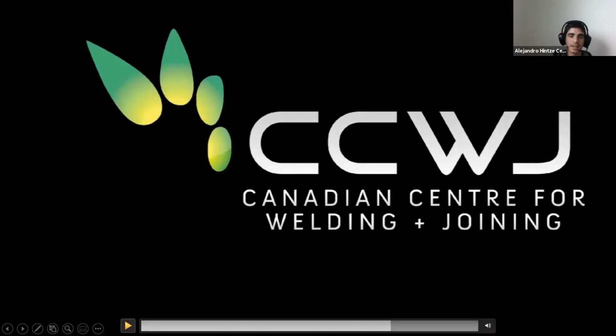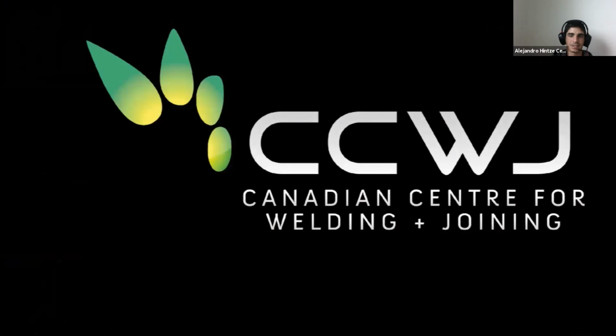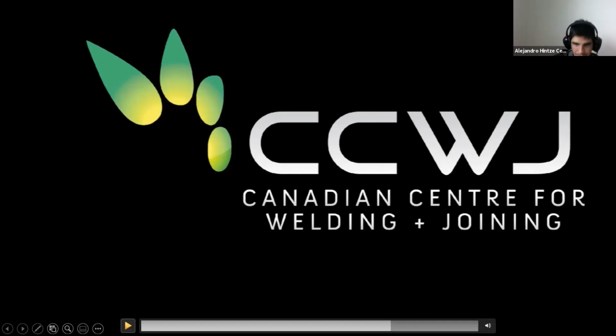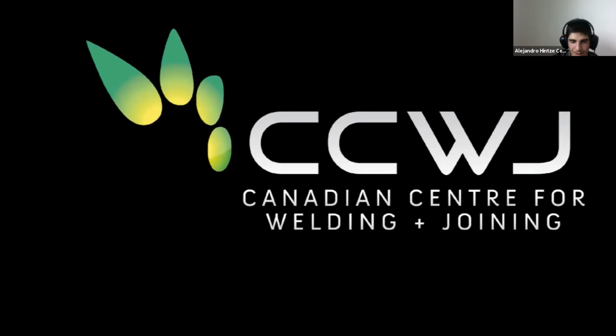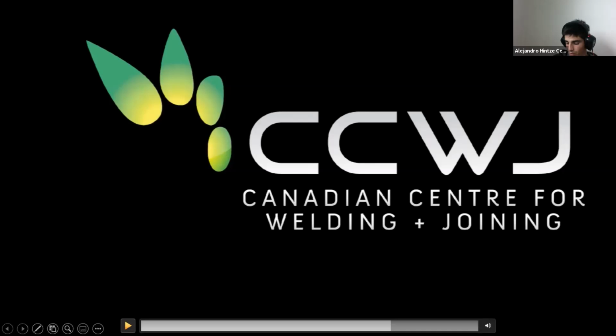So you can see, it sounds totally different. It's a really annoying noise when you're really close to the equipment. It can use higher amounts of CO2 compared to spray. It has a good penetration similar to spray, but again, same as STT, it needs power sources that are state of the art. They require high tech, advanced power supplies. So that's one of the cons, you can't do this with the machine that you buy. I don't want to say Canadian Tire, but in any place, it needs specialized equipment to do this.